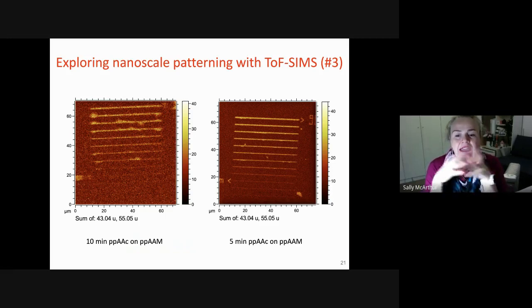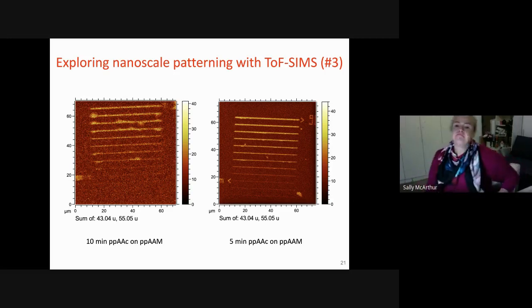And you can see here in the first instance, the thickness of that plasma polymer film that we're depositing in that second deposition actually matters. So in this side here, we're looking at a film that's been deposited on top of the allylamine of acrylic acid for 10 minutes. And then in this side, we've only deposited for 5 minutes. So the film is half the thickness. For us, that 10-minute film would probably produce a coating that's about 40 nanometers thick. So 5 minutes produces a film that's about 20 nanometers thick. There is just a direct correlation between deposition time and film thickness.